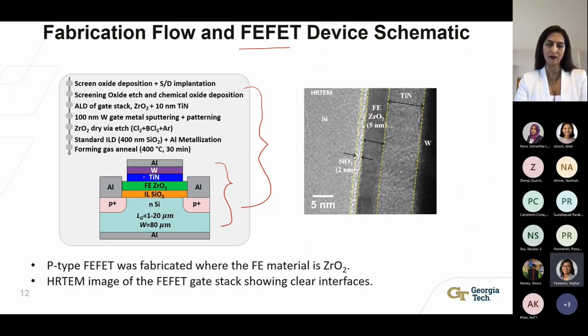Once this process flow was developed, for the first FeFET we made, we used ferroelectric zirconium oxide as the ferroelectric material because at that time we were still working with zirconia. This zirconium oxide was deposited by ALD by Tokyo Electron. This is the HRTEM image of the gate stack of our fabricated FeFET, which shows clear interfaces. I would also like to point out that the transistor gate length ranges from 1 to 20 micrometer. The reason we decided to make long channel transistors is because we wanted to understand the FeFET device physics due to the ferroelectric physics only, and not because of other effects like short channel effects.